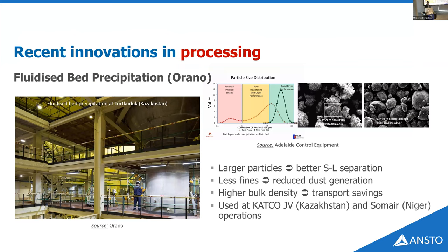And the last part in terms of innovation is fluidized bed precipitation that's been developed by Orano. They've used it in Kazakhstan at the KATCO operation or joint venture, and then at the Somaïr operations in Niger. The idea here is that you're basically growing larger particles, okay? And the larger the particles, the better they separate from liquor. Also because they're larger, in the drying process and when it goes into the calciner, there's less dust generation. And they've stated that it has a higher bulk density, so they're able to pack more into drums and put more drums into containers. The Somaïr operation has been stated to give them about maybe $2 to $5 per pound savings previously. So it's quite significant for them.